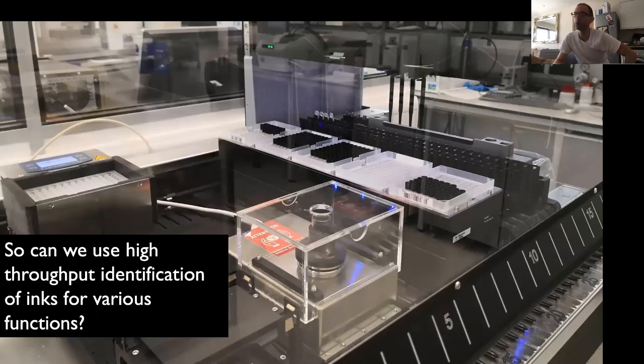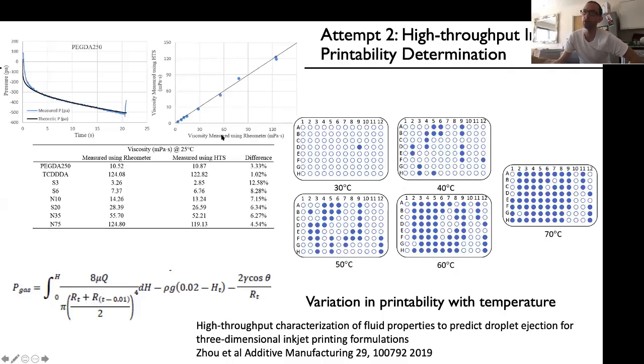is to then bolt on a high throughput identification of printability, specifically in this case for inkjet, but we have variants for other 3D printing systems as well. And so our system was a very simple system, really. We used a liquid handler to automatically aspirate and dispense target liquids, target monomers, and then using a pressure drop balance, a force balance to look at the pressure over time for a given flow rate of material, and extract out of that what the viscosity must be, and then calibrated that against known materials.